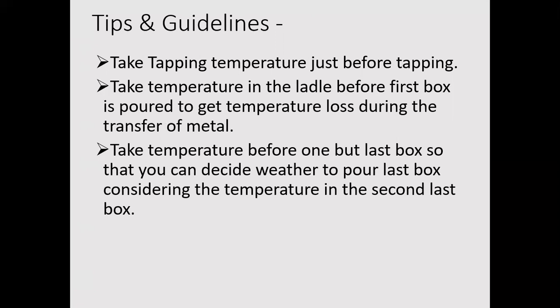Take tapping temperature just before tapping. Take temperature in the ladle before first box is poured to get temperature loss during the transfer of metal. Take temperature before the last but one box so that you can decide whether to pour the last box considering the temperature of the second last box. So it is very important.